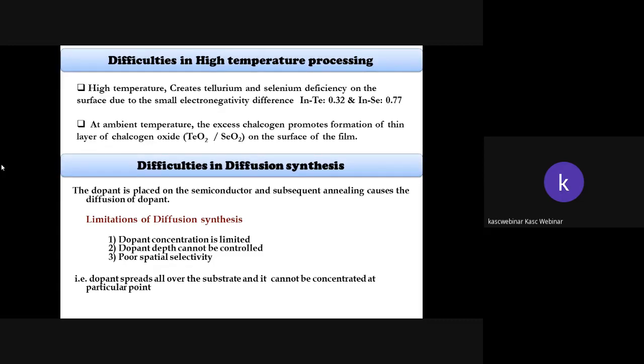And what are the difficulties in the diffusion synthesis method, even going for the conventional process? Actually, the dopant is placed over a semiconductor material or a particular selected material, and subsequent annealing causes the diffusion of the dopant. And the limitations of diffusion synthesis are that the dopant concentration is very, very limited. Suppose you have chosen the conventional technique, the dopant concentration is allowed only to a profile of a few nanometers or only a few angstroms. And the dopant depth cannot be controlled very easily. So this depth may follow a Gaussian distribution, and there is poor spatial selectivity also.